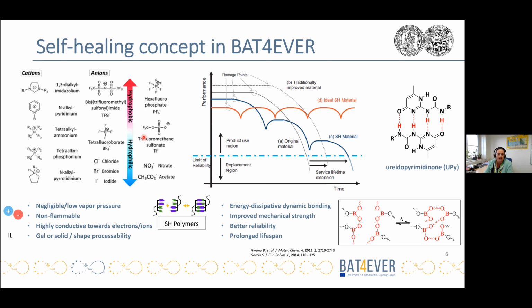them more solid. There are in principle two ways to combine ionic liquids with polymeric materials. Firstly, we can just physically embed the ionic liquid into a polymeric matrix, and these are so-called ion gels, or we can use an ionic liquid as a monomer itself and then produce the so-called polymeric ionic liquids.